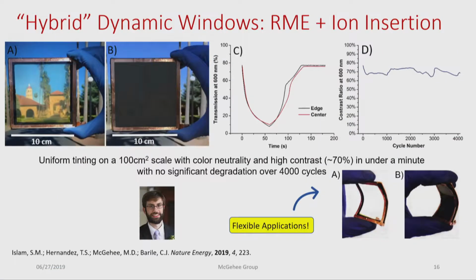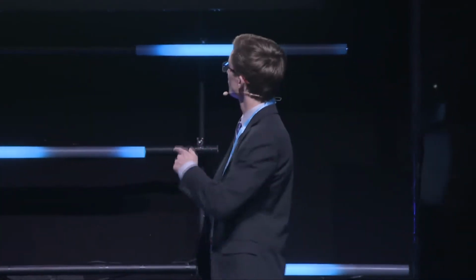So in collaboration with the Barile group at the University of Nevada in Reno, we were able to develop these hybrid dynamic windows that can switch from transparent to a color-neutral black in a few minutes over a few thousand cycles. One added benefit that we were able to show with this technology is its potential for flexible applications by relying on ITO and PET substrates.